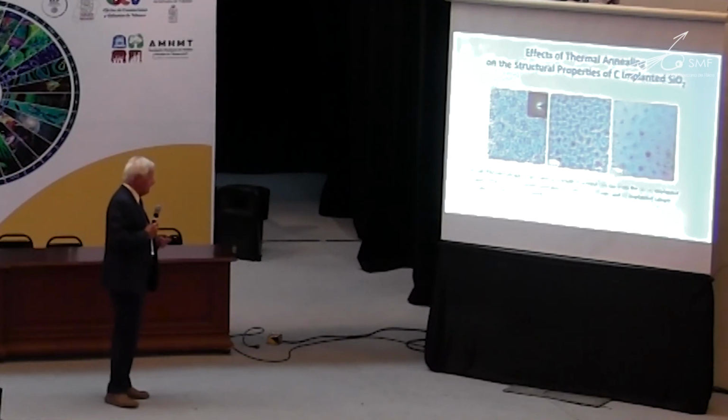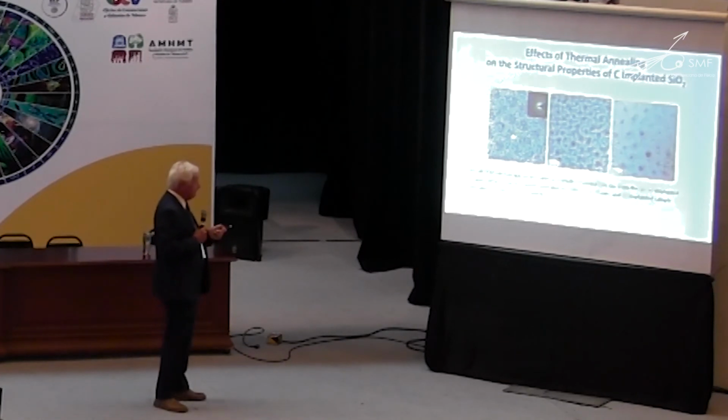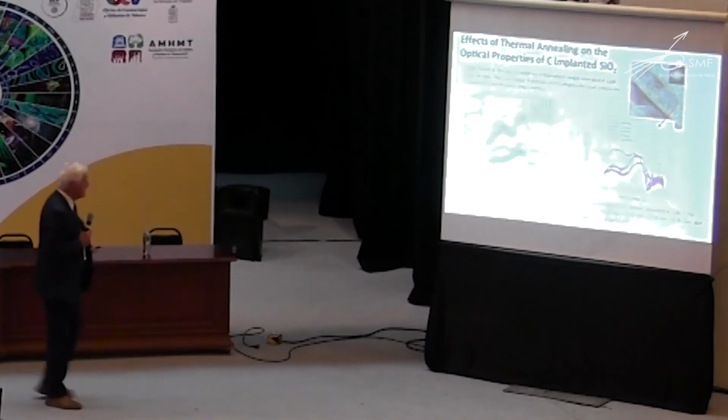What happens when you thermally anneal it? This is a high-resolution TEM micrograph image taken at a depth of around 200 nanometers from the as-implanted sample, the sample annealed at 1100 degrees for 10 minutes, and the sample annealed at 1100 degrees for 90 minutes. And you can see the nanostructures that are present there. Next slide.